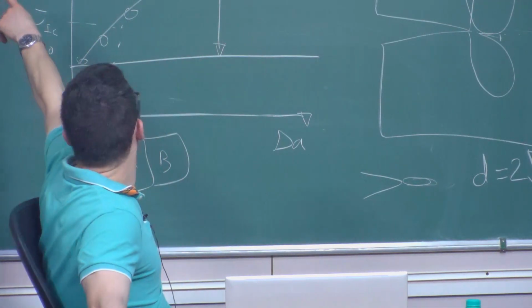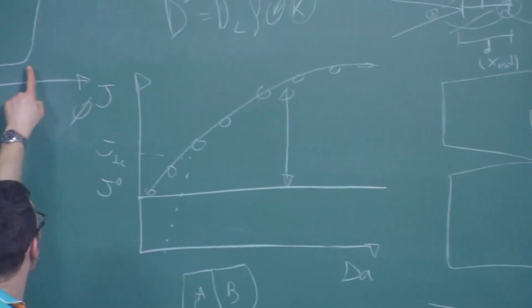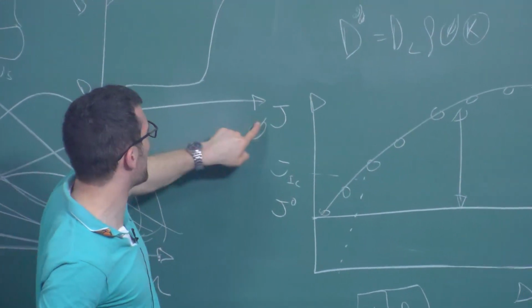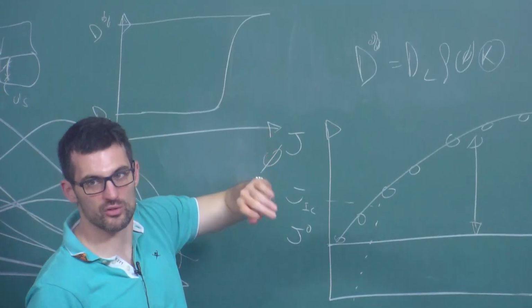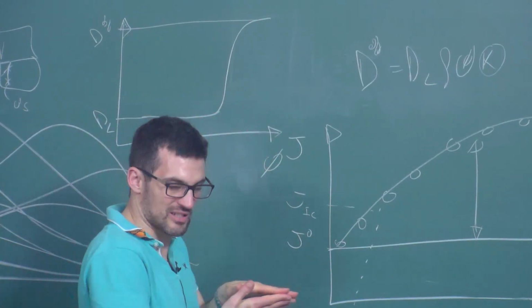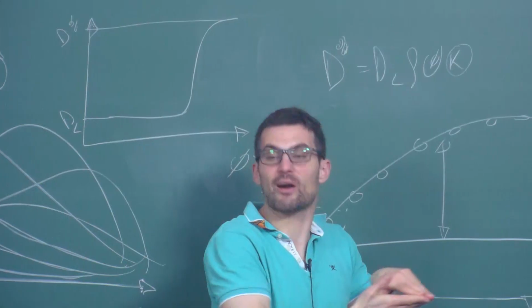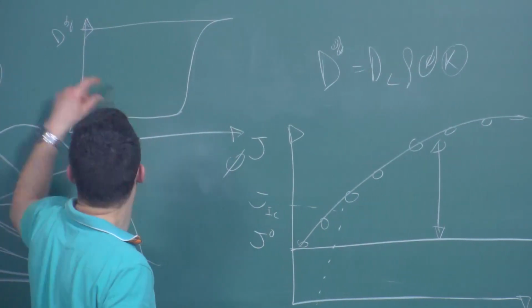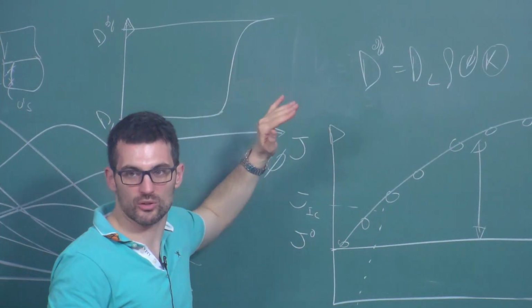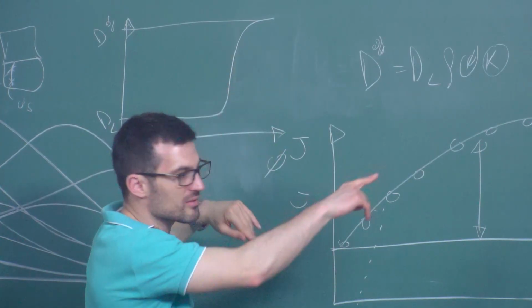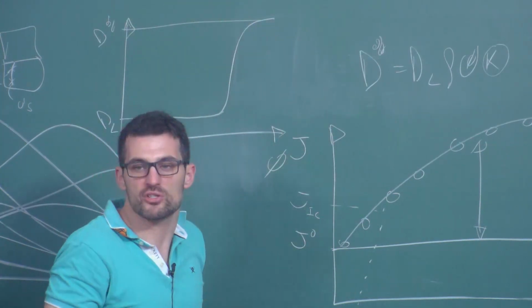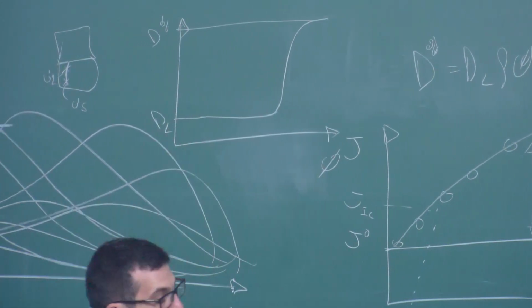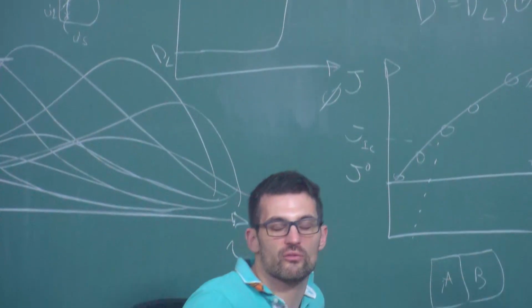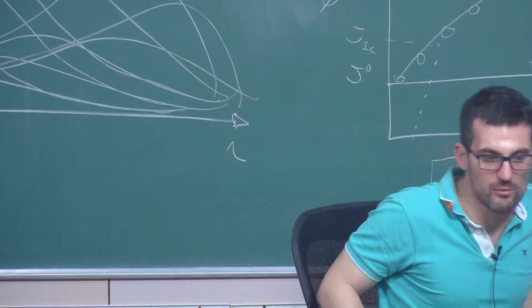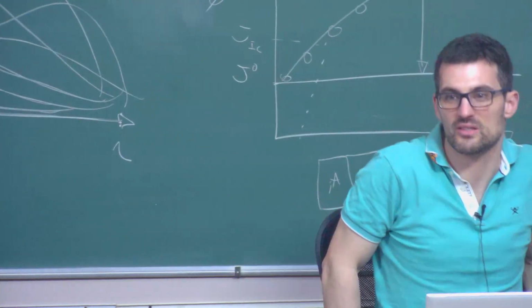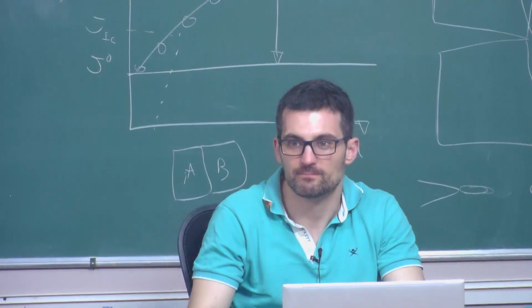A little bit the same goes for here. If you follow this approach, you want to pick this. This only happens in phase field regions that are very high, so it doesn't affect your results. The effect is that it's capturing the hydrogen growing with the environment following, which is what happens in physics, but what value you pick here is not important. You need to pick a value that is big enough to see this, but not so big that it will cause you convergence problems. I think that's the idea. So for us, an order of magnitude increase seems to do the job. It doesn't give convergence issues, and we can see that the hydrogen is following the crack. That's the idea.